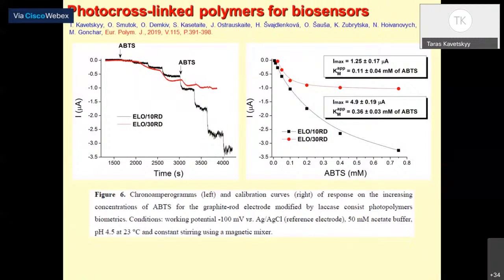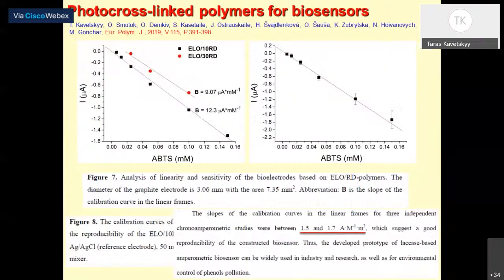Here we have the amperometric results for two polymers, and from these curves we estimated biosensor sensitivity. And we see that in the case of the first polymer, ELO/10RD, we have the larger sensitivity of biosensors compared to ELO/30RD. And the reproducibility of our biosensors is very good. We checked three independent amperometric studies, and the changes were between 1.5 and 1.7. It is in the normal range. So these biosensors have good reproducibility.